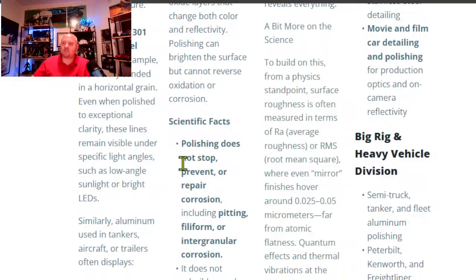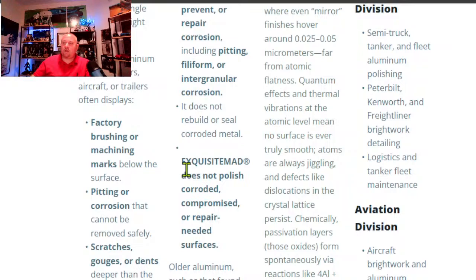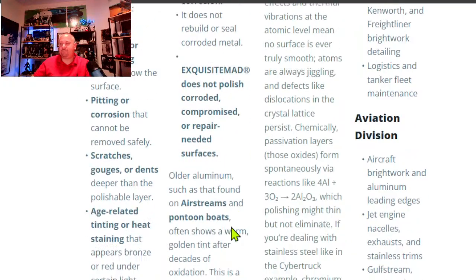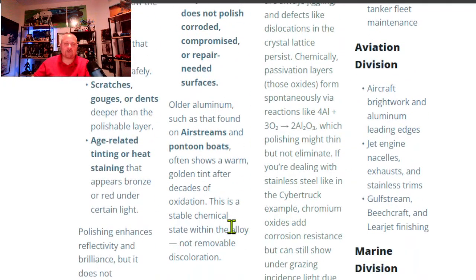Scientific facts: polishing does not stop, prevent, or repair corrosion, including pitting, filiform, or intergranular corrosion. It does not rebuild or seal corroded metal. We do not polish corroded, compromised, or repair-needed surfaces. That means if there's a crack, we're not messing with it. If it's so thin, we're not going to do it. And if something is so messed up and has not been maintained, we reserve the right to terminate service right then, because we can't polish something that's too far gone.